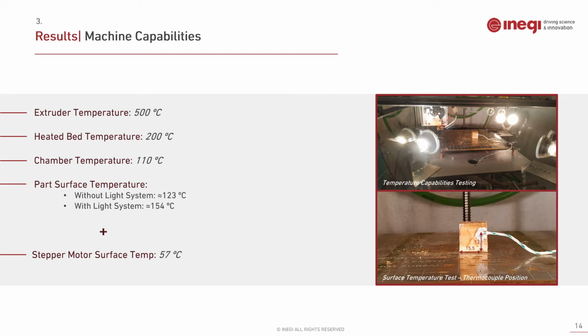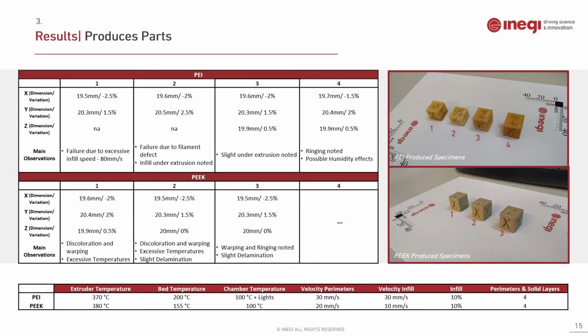And with a maximum reached temperature in the environment, we measured a motor temperature on its surface of 57 Celsius degrees, which we deem to be acceptable since a good estimation for winding temperature is adding 30 Celsius degrees to the surface temperature, which leaves us at around 90 Celsius degrees, which is well below the 130 Celsius degrees which is deemed to be the maximum for winding temperature. So, in general, we could state that our machine reaches all the specified requirements to produce parts in the high-performance plastics defined. In terms of the parts produced, we were successful in producing parts in both PEI and PEEK.